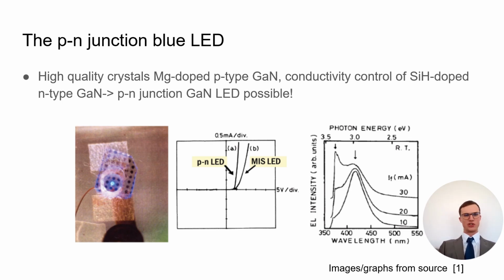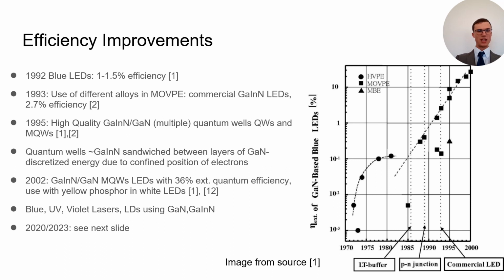Speaking of efficiency, this p-n junction LED was also much more efficient than the MIS LED in the past, as you can see from the plot in the middle. On the last slide, you saw the world's very first p-n junction blue LED. At 1 to 1.5% efficiency, it was good for its time, however nothing compared to what we have today. Already 1 year after its invention, in 1993, Nakamura et al. used different alloys in the metal organic vapor phase epitaxy growth method to gain 2.7% efficiency using gallium indium nitride. This is one of the benefits of this growth method, that you can control the alloy composition. So you can try new things and improve your material.